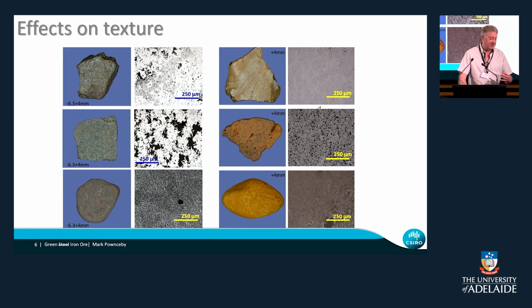The other thing that we need to consider is that all this alteration has a significant effect on the texture of the iron ores. So in this slide here, the three that go down the left side are all hematite particles. This is reasonably high-grade hematite. The top one is really dense hematite. This would be your lump ore that we would be really after, really high grade. The bottom one is still hematite, but it's a lot more porous, and you can see the microscopic images of these. The top one's really dense, then the middle one's microplaty hematite, and the bottom one's really, really microporous. So that's sites where impurities can get in.